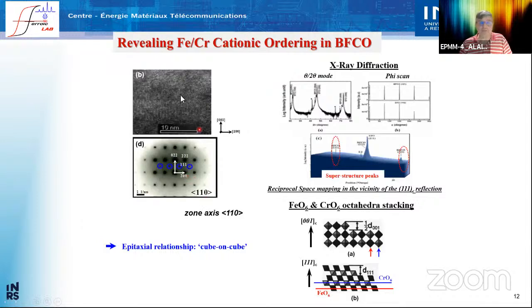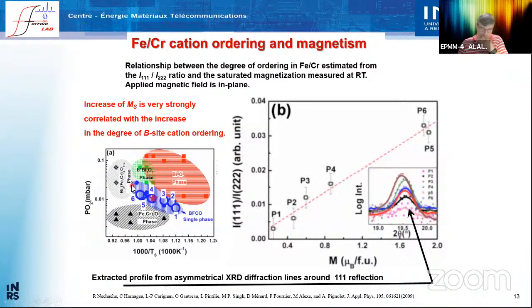As you can see, you really have a cationic ordering. You can see here the XRD spectra, where you see the 2 superlattice peaks. You see the same thing in the electron diffraction pattern, where you have the superlattice spots. And so even experimentally, you do have a certain cationic ordering happening. And we believe this is happening because the strong repulsion between the iron-iron cations would be decreased drastically if you put a chromium atom in between. So this is actually what creates the ordering.